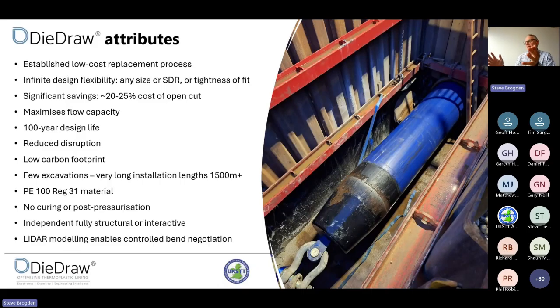So, the attributes of die draw, and most of these are also relevant to the other PE lining techniques. It's an established low-cost replacement process. It's not refurbishment, it is actually replacement, because the smoothness of polyethylene means that even an SDR17 going inside an old ductile iron main, the reduction in bore is more than offset by the smoothness, so that you actually have a greater flow capacity. So anything SDR17 or thinner, if it's a tight fit, will have a better flow capacity than the original pipe.